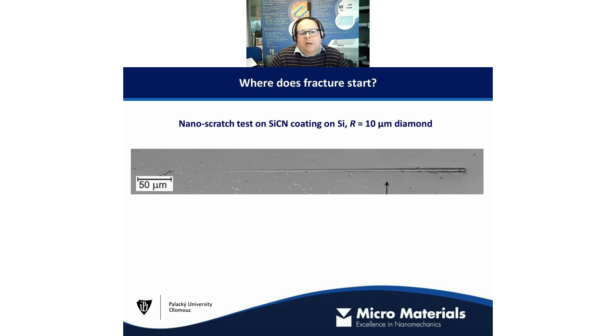This is a scratch test on a silicon carbonitride coating using a 10 micron radius diamond probe. It's a rather nice SEM image here of our scratch track. If we take a look at this, we can see some cracking that commences about here. From our indentation system, from our depth and friction scratch test data, this is pretty much where we see an instrumented initiation of failure. But the question is, is that really the onset of failure, or is there something happening beforehand?